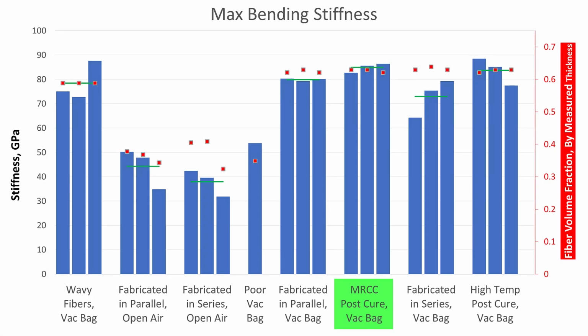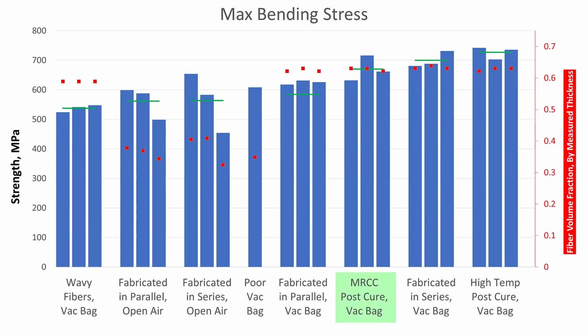The samples which were post-cured according to manufacturer's recommended cure cycle were stiffer than the samples which were not post-cured, but were similar to the samples which were held at a higher temperature for longer. The post-cured samples had strengths in between the two non-post-cured vacuum-bagged samples, both in absolute terms and relative to expected strength based on fiber fraction. The high-temperature cured samples had the highest strength and high stiffness, indicating that they may not have been held at high enough temperature or for long enough to begin to degrade the matrix.